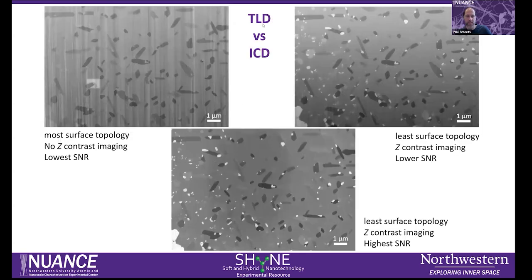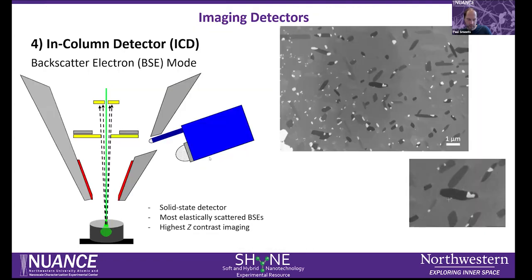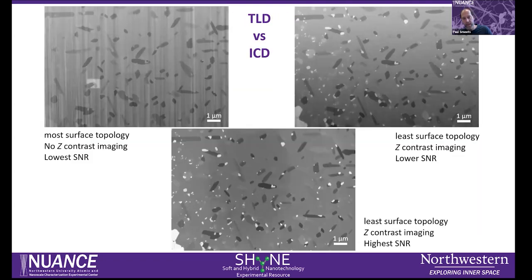So if we compare, for example, the TLD with the ICD, these can be acquired simultaneously. The TLD detector gives you really that surface topology in SE mode, where there's no apparent Z contrast imaging, versus the ICD detector, which is a solid state detector. It gives you the highest Z contrast and highest signal to noise, and we barely see that curtaining effect present here.